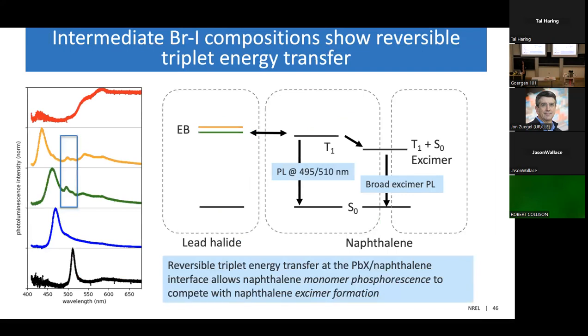So for these intermediate compounds shown in orange and green, the exciton band in the lead halide is pretty close in energy to the triplet of naphthalene, such that we might even have some back and forth energy transfer across this interface. And this reversible energy transfer allows the monomer phosphorescence at 495 and 510 nanometers to compete with the excimer formation. So that's why we start to see these extra features showing up in these spectra.